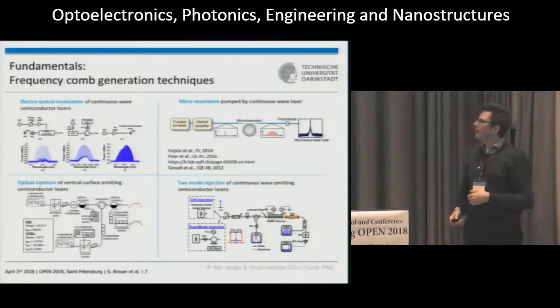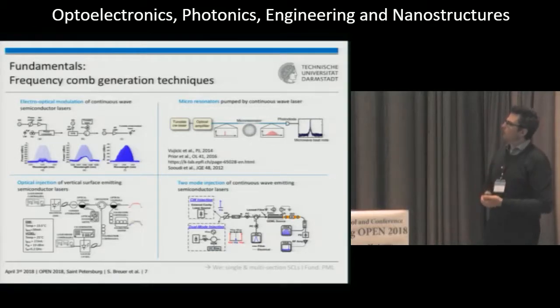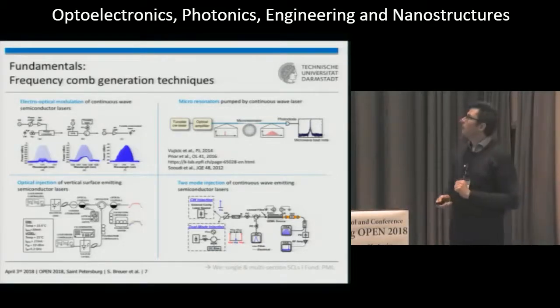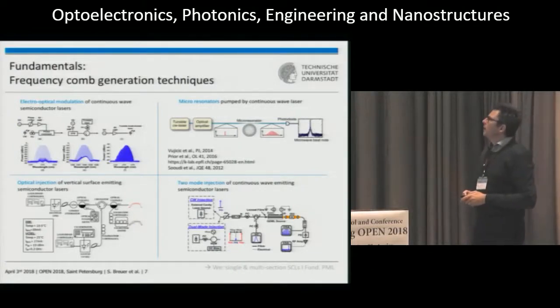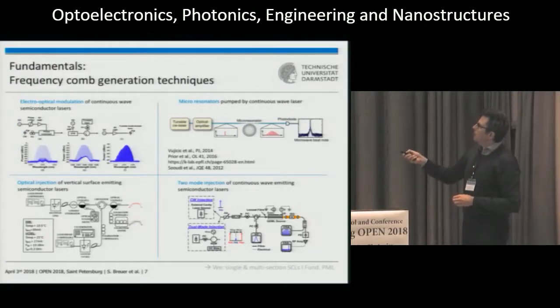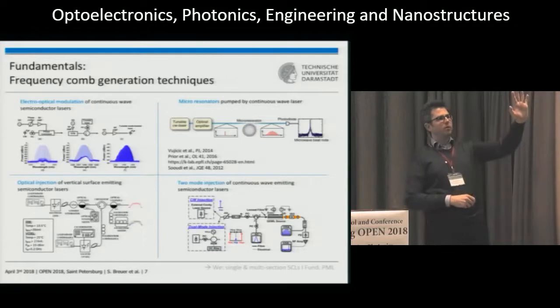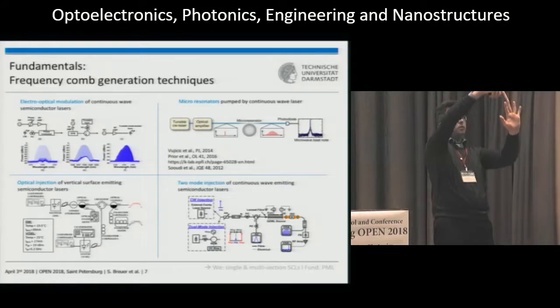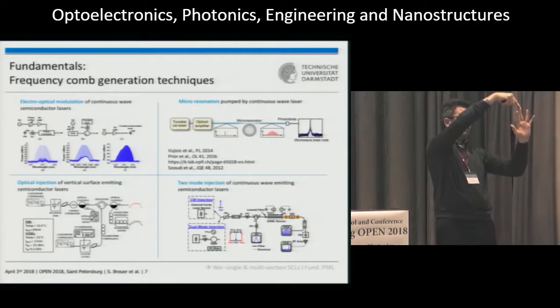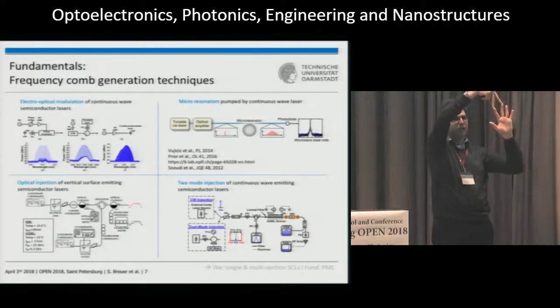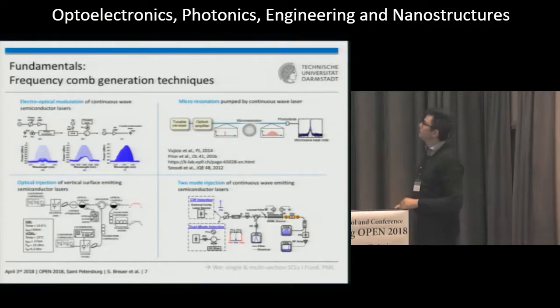However, well, it's there within the commercialization. The second group is in Spain, the group of Prior. That's a concept developed for a two-section mode-lock laser, a dual mode injection, where you basically have a mode comb that can jitter around. You can inject a mode here, then you say to the laser, hey, stop please with the jitter, and this mode will be fixed, the others will be jittering. But if you inject a second mode here, then of course the laser has no chance at all to jitter anymore, because these two fix the separation. This is the concept basically.